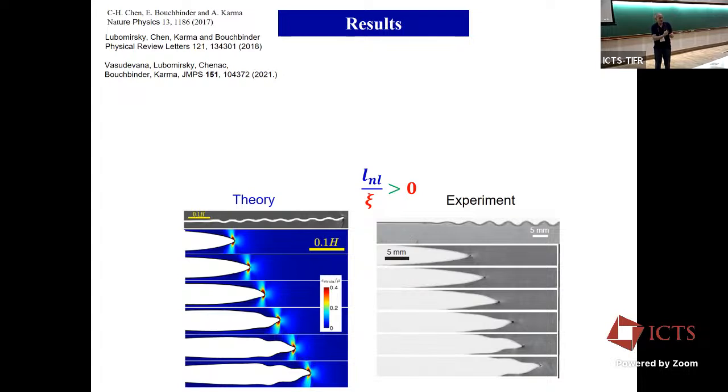So initially, as the crack goes through the strip, it doesn't know about the boundaries, so it gets faster and faster. Once it gets to the strip, the waves start to come back from the vertical boundaries, and they tend to close it, which makes it look like a tadpole. Okay.